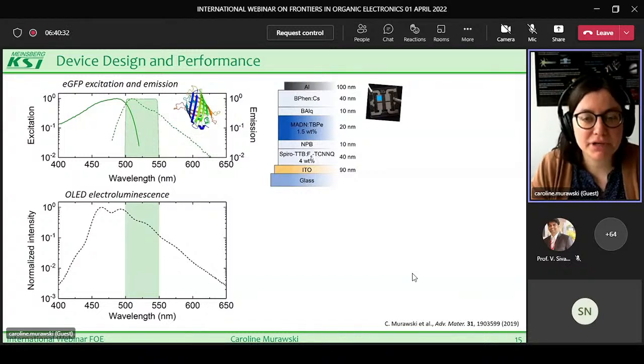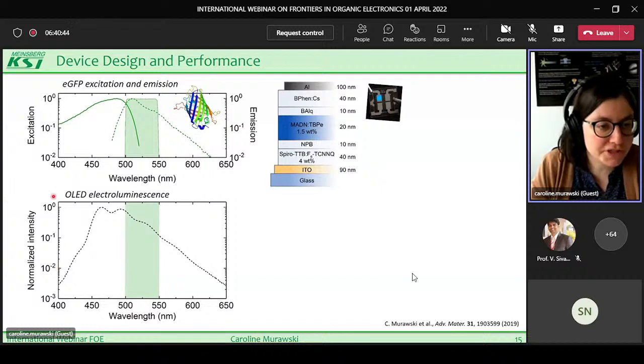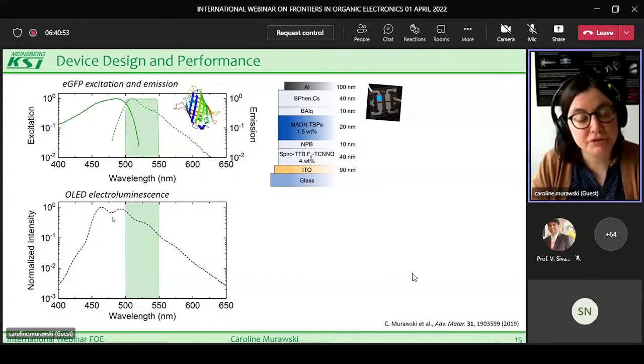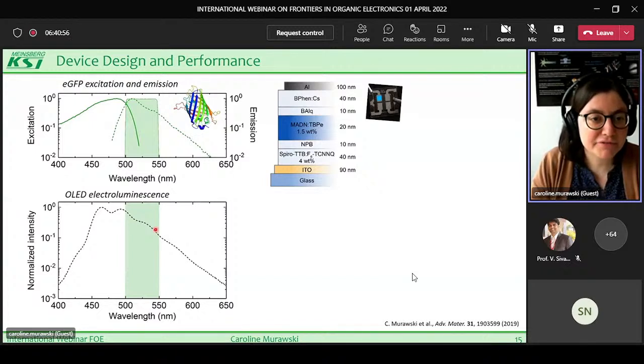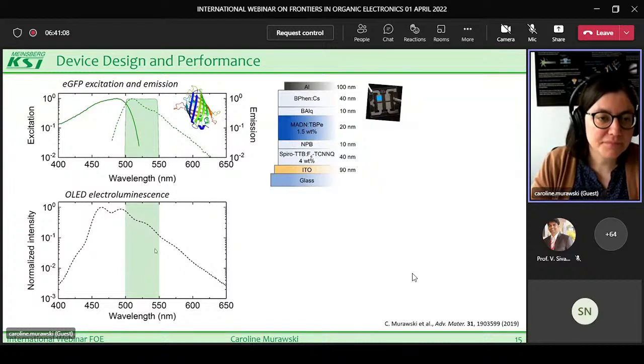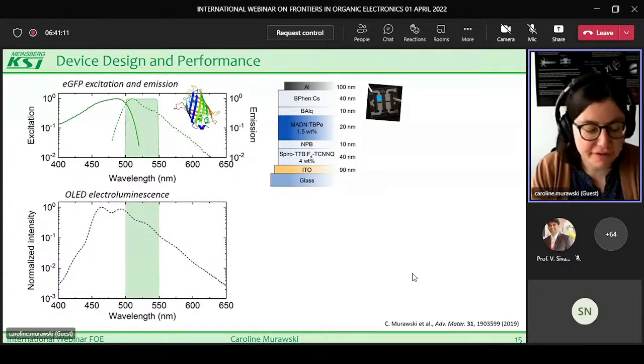Now, we want to apply OLEDs for this purpose, and we've used, again, a similar structure to what I showed you before already. But if we look at the OLED electroluminescence spectrum, and this is now shown on a log plot here, this spectrum looks extremely broad in this case. We see that we have a very good overlap with the excitation spectrum, so we can have pretty good excitation, but we also have very strong overlap of the OLED emission in the wavelength regime where we only want to see the emission from the fluorophore. So we basically need to get rid of this area of this emission of the OLED in the green wavelength regime.